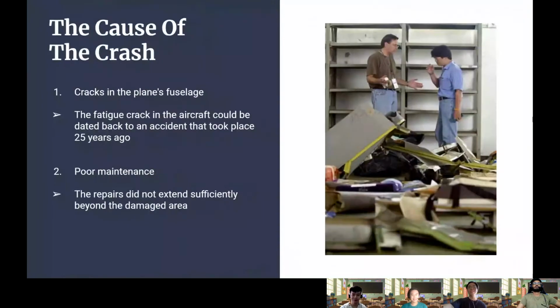Okay, thank you, Wei Xuan. Now I will talk about the cause of the crash, which is because of the cracks in the plane fuselage, as well as the poor maintenance, which killed all 225 people on board. For the cracks in the plane's fuselage, after more than 2 years of analyzing information gathered from the plane's flight data recorder, air traffic control, wreckage distribution, and a reconstructed section of the fuselage, the Aviation Safety Council (ASC) concluded that a 180.34 cm crack on the fuselage resulted in the in-flight breakup at the altitude of 10,668 meters, killing 206 passengers and 19 crew members. According to the ASC, the fatigue crack in the aircraft could be dated back to an accident that took place 25 years ago.